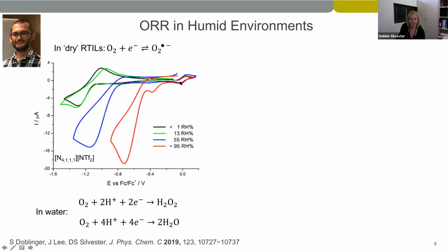We have ferrocene in here as an internal redox couple, so you can see the shift in the potential. What's happening here is that the mechanism in water follows either a 2 electron or a 4 electron reduction depending upon the pH. As we're adding moisture to our gas stream, that's dissolving into the ionic liquid, and we're changing over from our dry ionic liquid mechanism to a more water saturated environment.